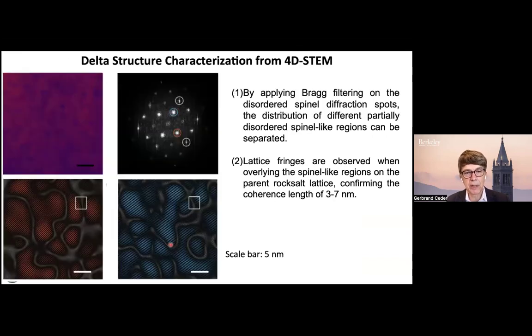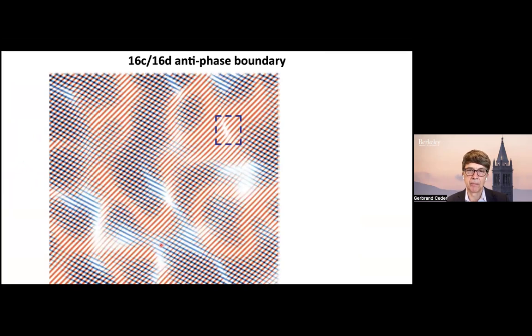And what you're seeing here is the impingements of these variants on each other. And this microstructure is remarkably stable. If you look at this at longer times, it still looks exactly the same. So it does not coarsen, which still puzzles us. This maybe because there's very little energetic driving force to coarsen, because the whole material is transformed to these spinel domains. If you actually look at enlargement of the stem, you actually see antiphase boundaries.